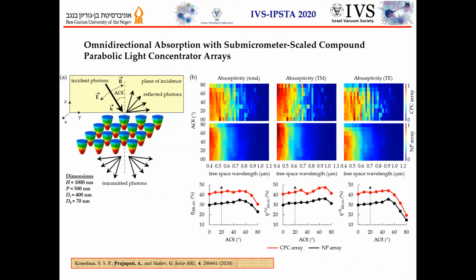In this study, we consider a substrate-less CPC array, which is in figure A, and the dimensions are presented here. The polarization of illumination is also shown, the electric and magnetic field, in which TM along the X direction is shown for an example. Figure B presents the angle of incidence dependency of the CPC array total absorptivity spectra, which is averaged over both polarizations, as well as polarization resolved absorptivity spectra, and similarly the corresponding spectra for nanopillars. The color maps below are for nanopillars and the color maps above are for CPC arrays.